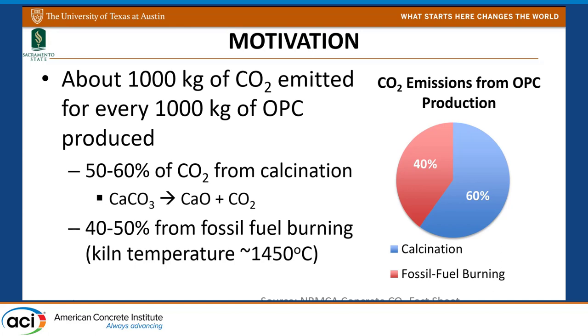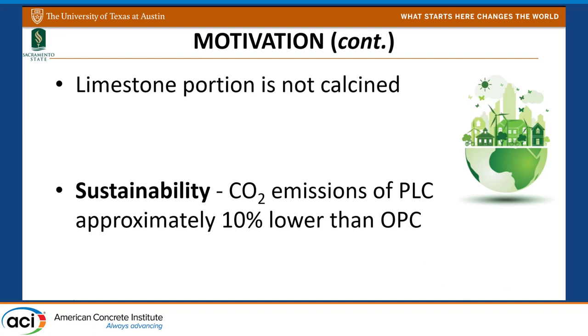The main motivation behind this was sustainability benefits. You might be familiar with the CO2 emissions and how cement production is a very energy-intensive process. For every pound of cement that we produce, we release about one pound of CO2 emissions into the atmosphere. About 50 to 60 percent of that comes from the calcination process, and the rest comes from having to get the temperature very high to trigger the chemical reactions we're looking for.